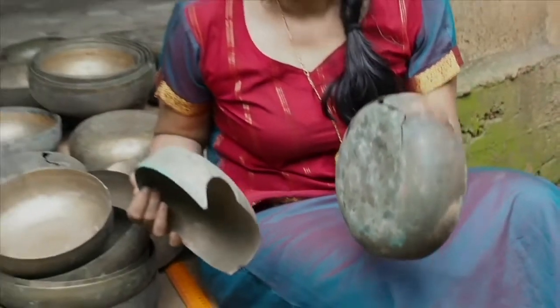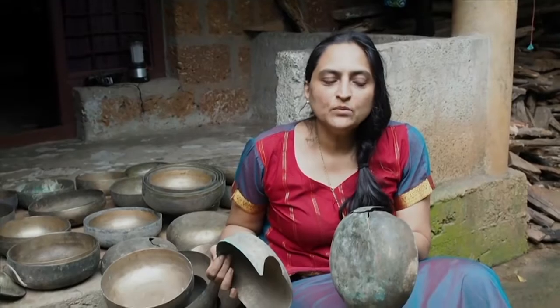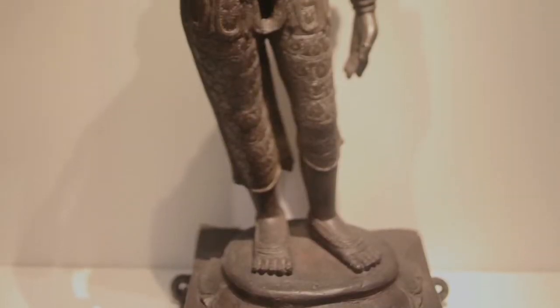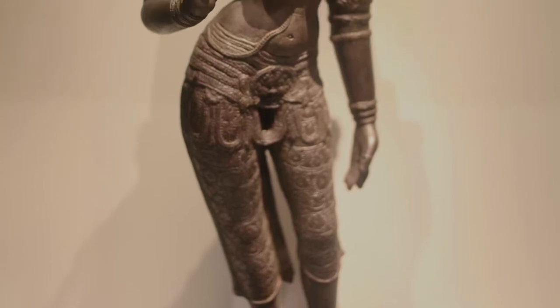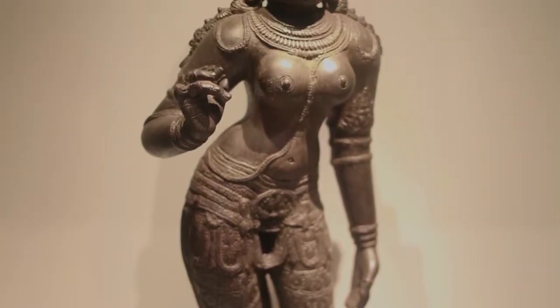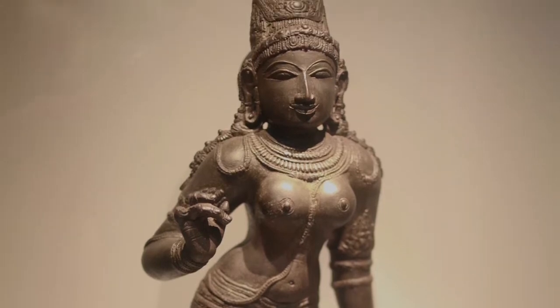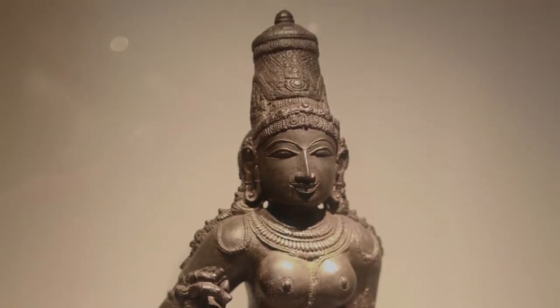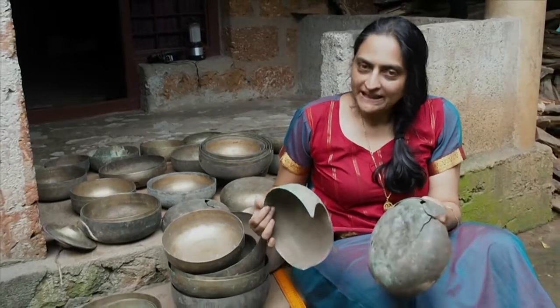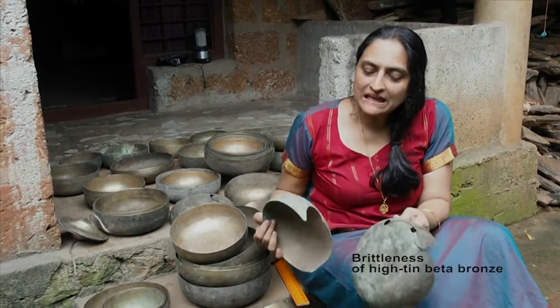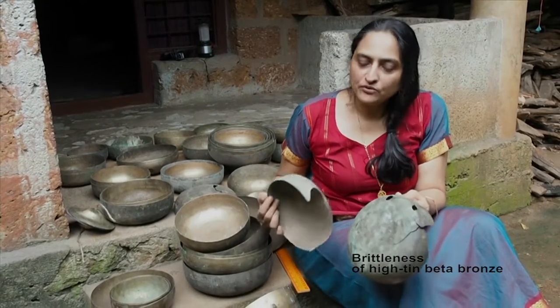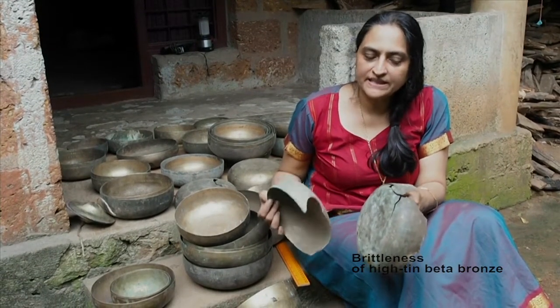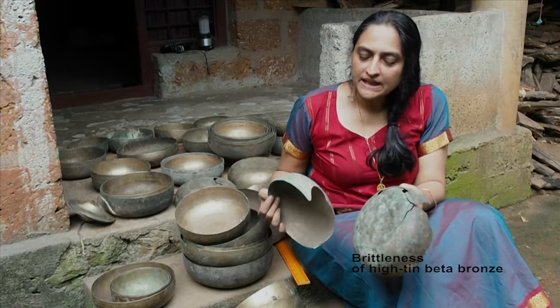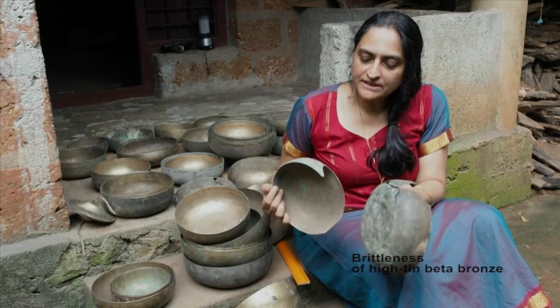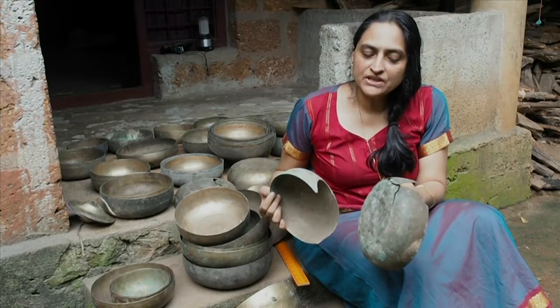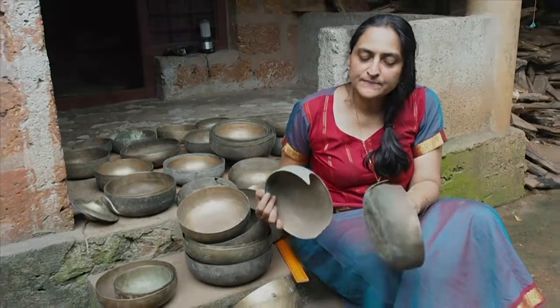When we look at bronze, bronze with a low amount of tin, which is about 10% tin, is, as I said, the kind of material that we normally find in antiquity, which is called leaded tin bronze. For example, a lot of the Chola bronzes are leaded tin bronzes. However, as you keep adding tin, bronze actually becomes very brittle and breakable. And that is also why we don't find a lot of examples of bronze with a higher tin content in the ancient world. It was only in some parts of Asia, especially in India, and also in Southeast Asia and so on, that this high-tin bronze alloy was used.